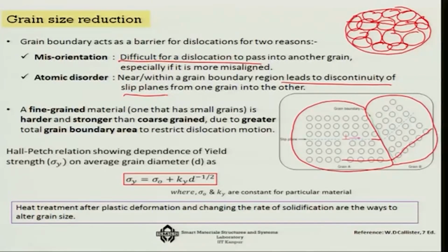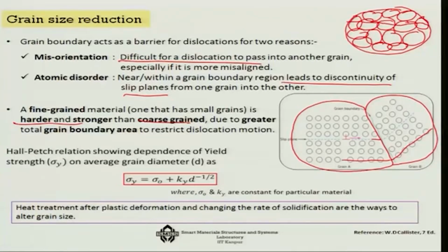Now, a fine grain material is harder and stronger than a coarse grain material, due to, as I said, the larger grain boundary area restricting the dislocation motion. This was first observed by Hall at the University of Sheffield, close to the 1950s. Hall observed this first in steel alloys, and later on Petch independently observed the same, not for steel alloys, but for other alloys. So, what Hall noticed is that the relationship between the yield strength and the average grain diameter d follows a nonlinear relationship, and there are two constants, sigma 0 and ky, which govern this relationship.